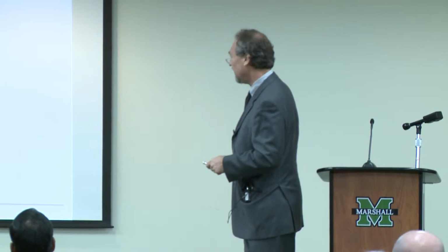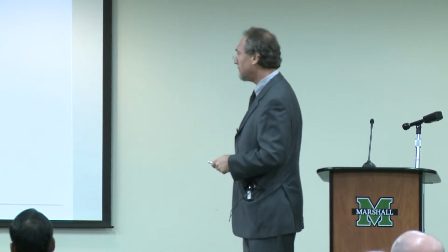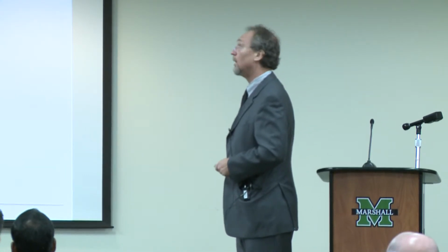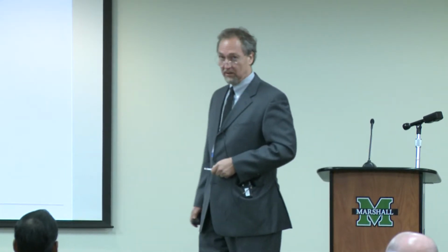It's niobium. Niobium is superconducting at about 9 degrees Kelvin. And its gap energy is 680 gigahertz. I'm producing 250 gigahertz. So the 250 gigahertz photons from the far-infrared laser don't produce any absorption in the niobium for physics reasons.